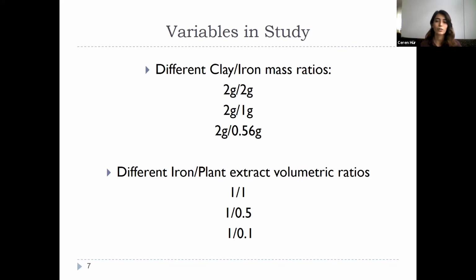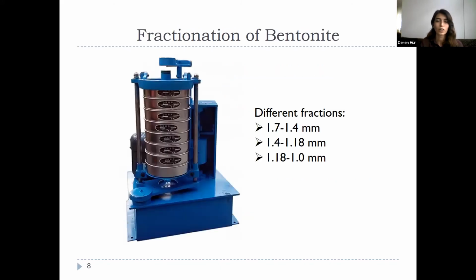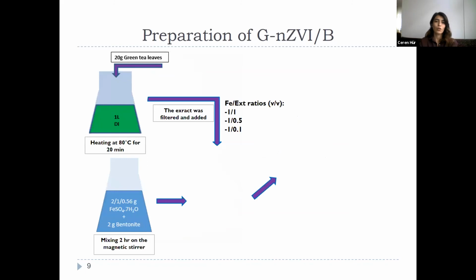Synthesis variables include different clay per iron mass ratios. These are 2/2, 2/1, 2/0.56 grams, and different iron per plant extract volumetric ratios, 1/1, 1/0.5, 1/0.1. Fraction of bentonite. Bentonite was sieved to separate 3 different fractions, as can be seen on the slide. Preparation of GNZVI.